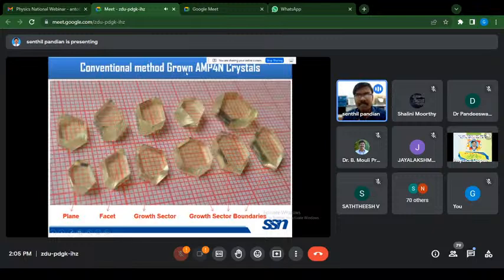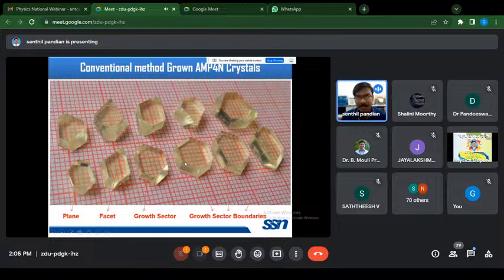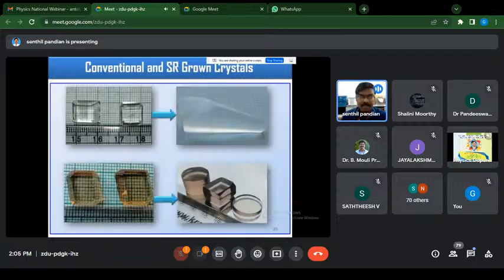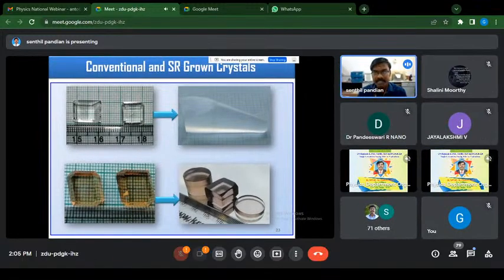And these are the conventional method grown AMP4N single crystal. So if you focus any one single crystal, conventional method grown crystal, all the crystals are having different planes, facets, grain and grain boundaries. But for application point of view, phase matchable portion is only useful, and other portion will be cut after cutting the phase matching angle. For devices like frequency doublers and optical parametric amplifiers, phase matching needs to be achieved. Otherwise, the conversion efficiency would be very low. So in this point of view, this Sankaranarayanan Ramasamy method, SR method, has given the solution, and it is possible to grow the crystal along its phase matching direction.